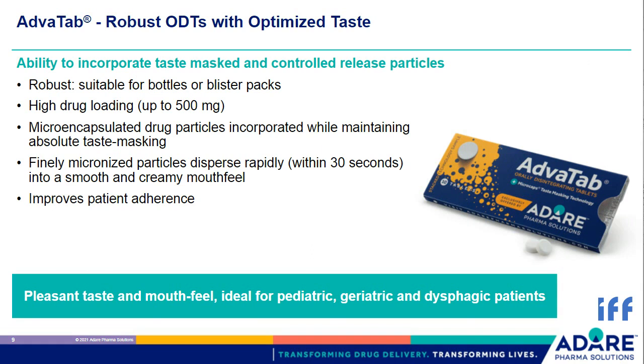But taste-masked particles originated with Optimum and Microcaps technologies can also be incorporated in an ODT, an orally disintegrating tablet. And to minimize the risk of breaking particles during the tableting process, jeopardizing the taste masking properties, a specific ODT composition and manufacturing process named AdvaTab was developed internally, leading to an ODT able to load a significant amount of active and disintegrate quickly in the mouth.